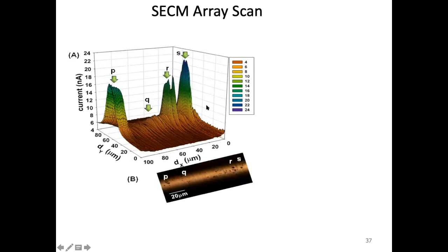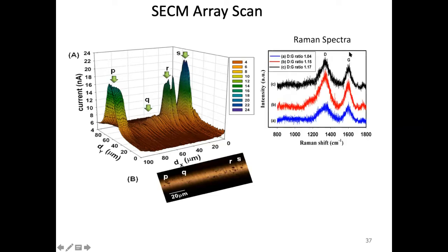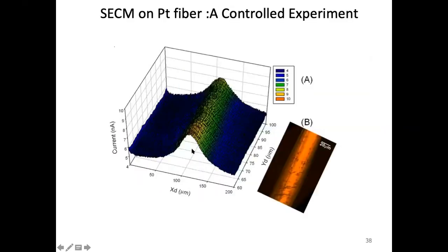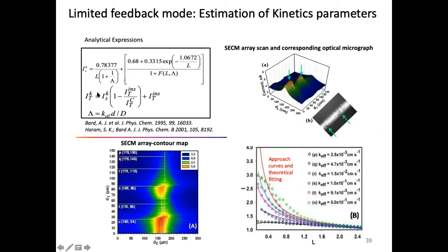And we substantiated this work with Raman spectra. We measured in situ Raman spectra, where we found that at those particular spots we get a stronger D band. You know, the D band is the defect band. It is responsible for pseudo sp2 or sp3 hybridized orbitals there. That means there's unsaturation at that point. So this was substantiated with Raman spectroscopy. Well, this is the control experiment with platinum. We did a lot of mathematics and extracted the concentration and the effective rate constant, or charge transfer, in this reaction.